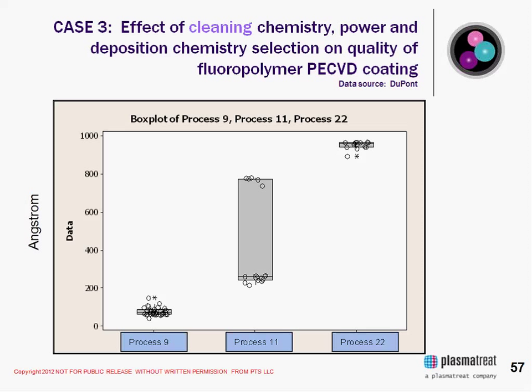There are some unique things that we've been doing with the siloxanes, which have selective adhesion properties. So they may bond to something, eliminating non-specific binding to something else. Same with functional chemistry. A customer may only want to bind something very specific. So an oxygen chemistry may provide too much variability depending on what the substrate is. So we may choose a more advanced chemistry that's going to provide a very specific chain or linker chemistry control to a specific functional group.